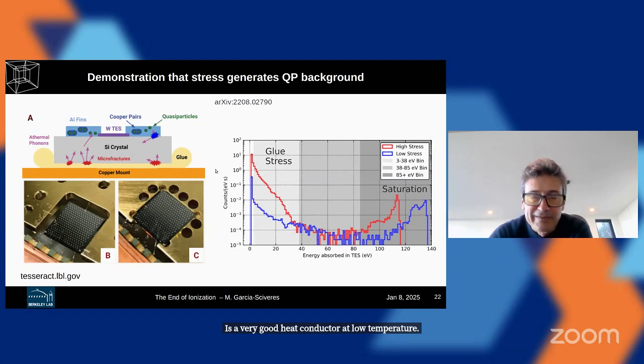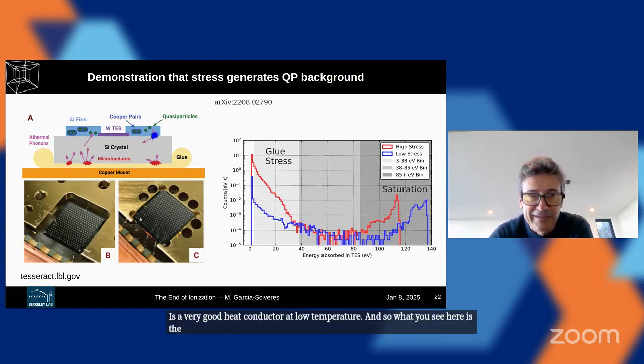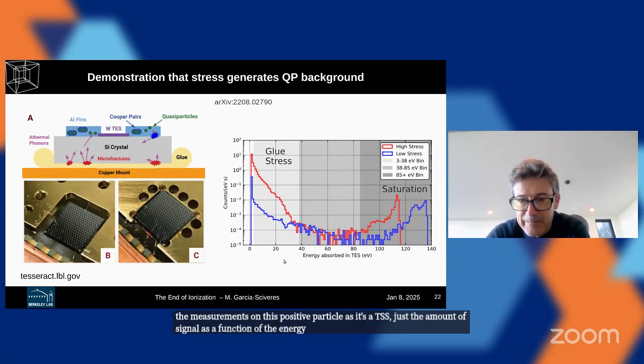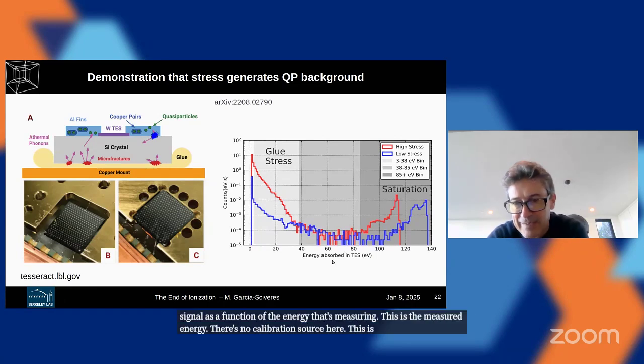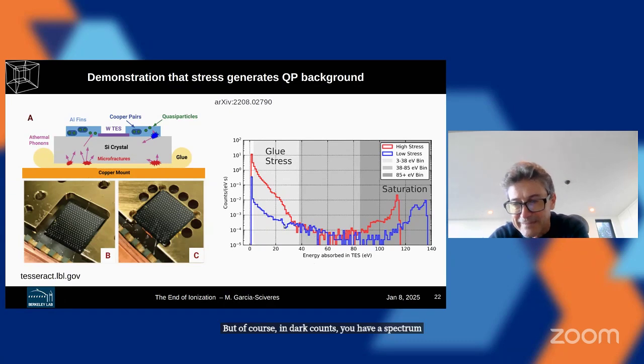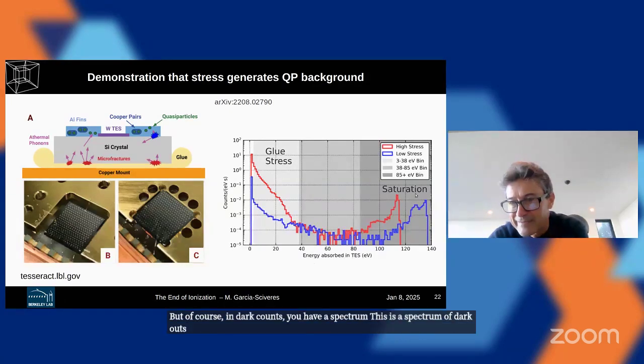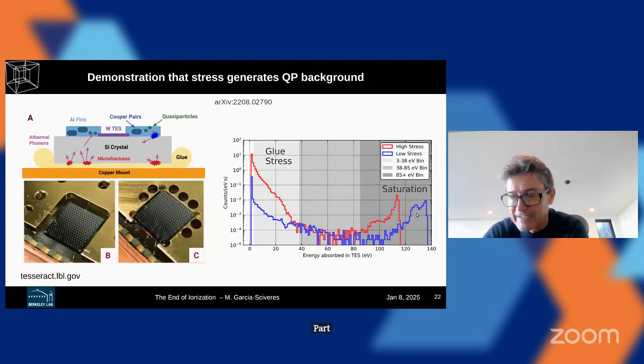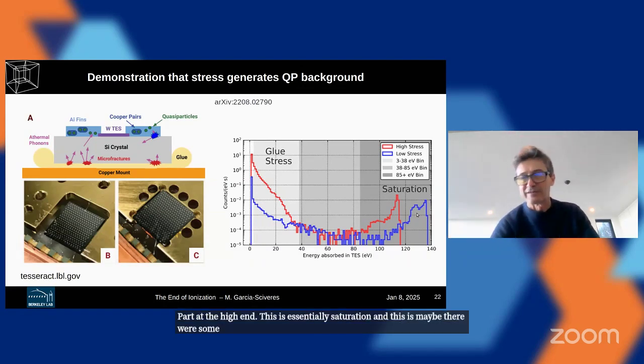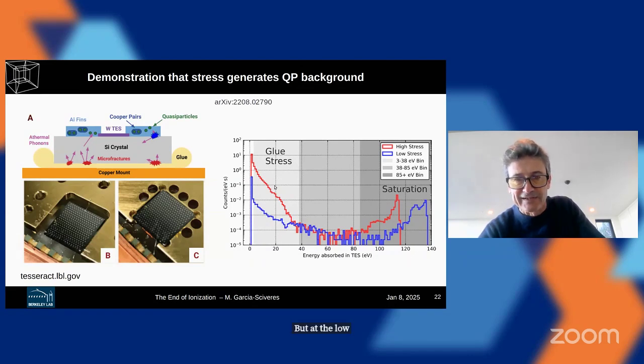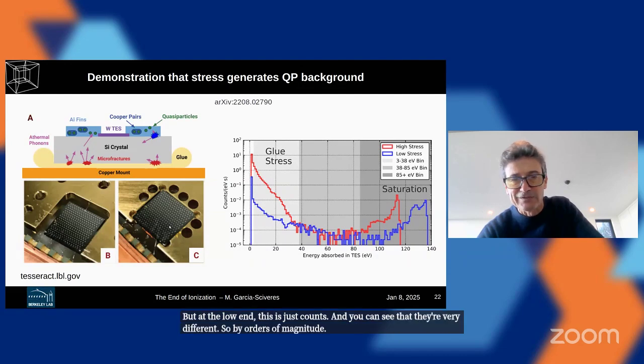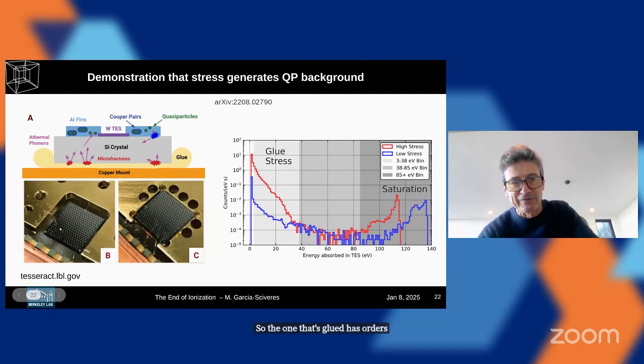And so what you see here is the measurements on this quasi-particle assisted TES. It's just the amount of signal as a function of the energy that's measured. This is the measured energy. There's no calibration source here. This is just dark counts. But of course, in dark counts, you have a spectrum. This is the spectrum of dark counts. Never mind this high part at the high end. This is essentially saturation, and maybe there were some cosmic ray events or some external background hitting the detector here. But at the low end, this is just dark counts. And you can see that they're very different, by orders of magnitude. The one that's glued has orders of magnitude more dark counts than the one that's hanging from wire bonds.